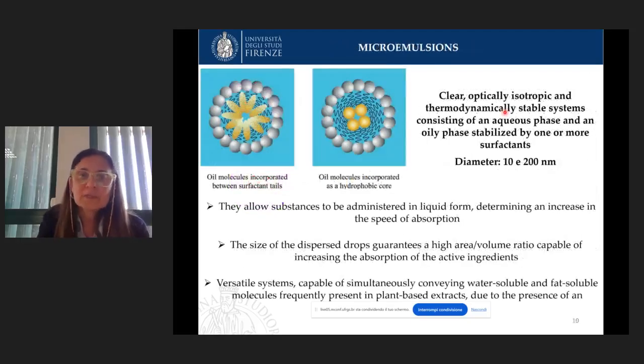Other nanoformulations important for delivering particular extracts, because they improve the solubility of different kinds of molecules, are microemulsions. Microemulsions, oil in water or water in oil, are clear, transparent systems, optically isotropic and stable, where a lipophilic or hydrophilic phase is surrounded by a high amount of surfactant. This formulation improves the solubility of the plant-based extract due to the presence of oil, but also of the high percentage of tenside around the inner phase.